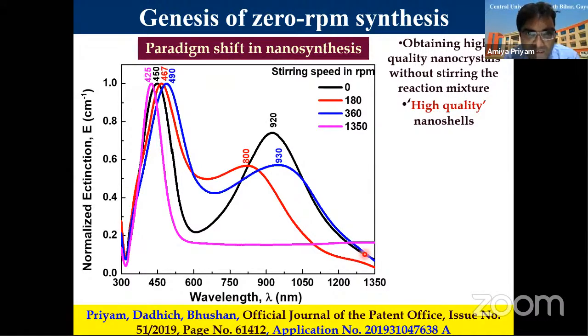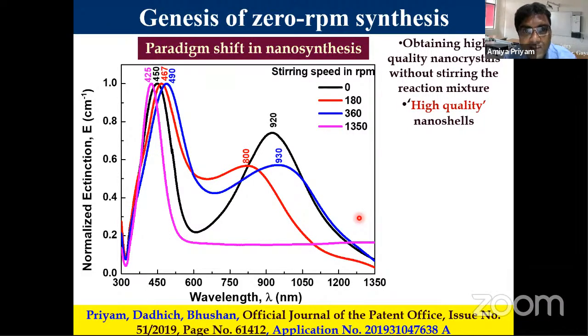Usually when you go to a synthesis lab to synthesize nanomaterial, it is always advised that you keep stirring your solutions. You must mix them homogeneously and keep stirring very well. Only then will you have a narrow size distribution, a nice peak will be observed, and the nanomaterial will be formed. But we are showing that there are certain synthesis methods, as in this one, where stirring is bad. You don't have to stir the solution at all.